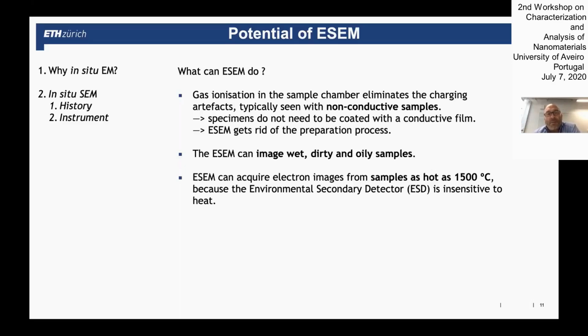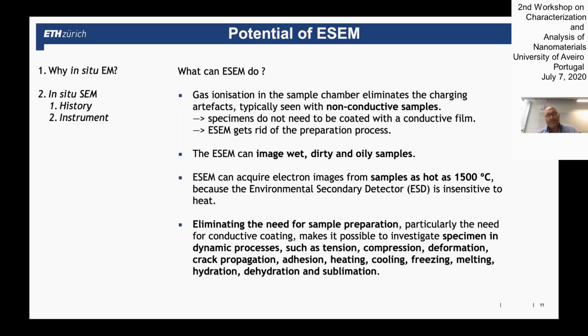And because you don't need to coat and you can put samples in the natural state into the microscope, you can do interesting experiments. You can, for example, heat up a sample. You can do stress testing and mechanical deformation and all these kinds of things. So it's a brilliant platform for in situ experiments because it offers a lot of space. When you think about a TEM, you have your objective lens and there's not enough space really to put more in between than just your sample. But in a scanning electron microscope, you could put fibers inside for light, you could put an AFM inside, there's so much space. So it's really a perfect platform for studying many different things in situ.